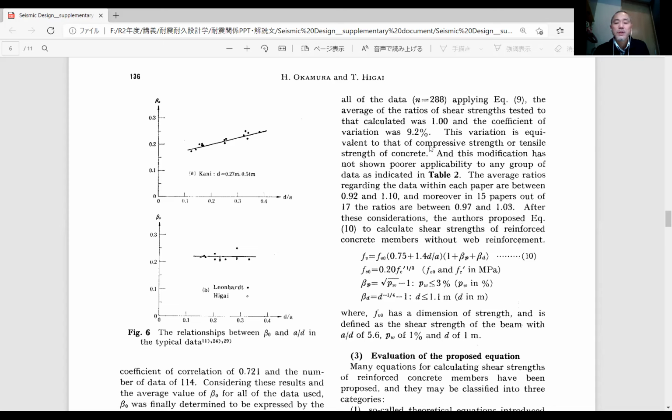Why? Sometimes the quality of the concrete specimen is not uniform. Sometimes the shape, for example, whether the bottom surface and top surface are parallel or not. It also depends on the technique of the testing person, right? Or maybe sometimes a tester will not take care of the loading speed specified in the specification. A compressive strength test seems easy, right? But even compressive strength experimental work shows around 10% COV. So from this sentence, you should feel how powerful their proposal is.